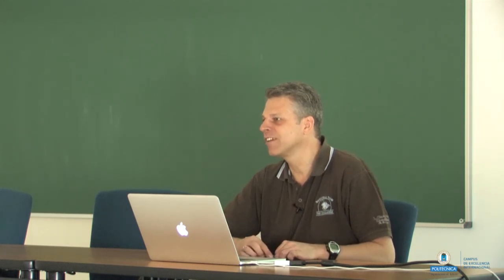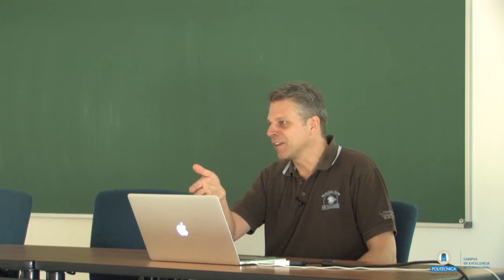Yes, this is completely right, and I avoided mentioning this during the session, but both your questions are perfectly right. And the final conclusion here also was welding without post-weld heat treatment is, well, not possible. But in your case, okay, it's not so difficult to heat it up to 700 C or so. Okay, you have to avoid some distortion due to tempering, but that's a smaller problem. The problem here is these 40 millimeter thick plates, which is more tricky. It also requires a heat treatment, that's clear.